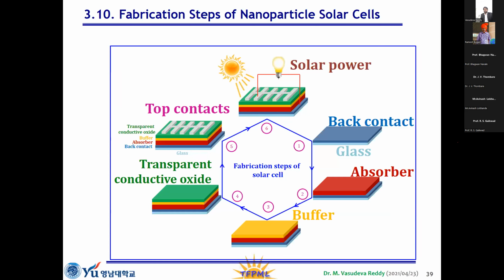Then the buffer layer. In general, previously, most people used chemical bath deposition, but the prospective methods like ALD and MOCVD are more promising to control the thickness of the buffer layer. And finally, the transparent conducting oxide. Here also we can use solution processes and also physical processes. Sputtering is a good technique for preparing transparent conducting oxide. MOCVD is also a suitable technique to prepare transparent conducting oxide.